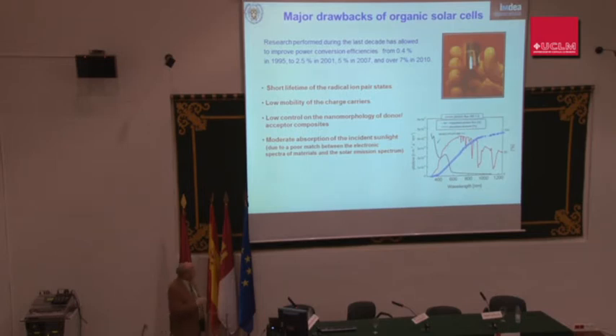Still, with this, the major drawbacks for organic solar cells, we could say that you can see here what has been the evolution of this one. So 5% was reached at around 2007. When we reported close to 3% in 2005, it was quite good indeed at that time. But these are the major drawbacks: short lifetime for the radical ion pairs, the low mobility of the charge carriers, these are open questions so far.